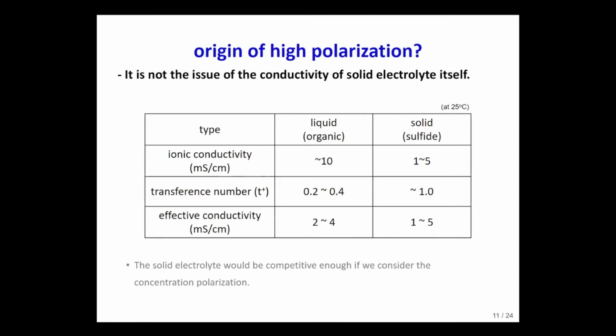Many people suspect that the lower conductivity of solid electrolyte is responsible for the low rate performance, but that is not true in this case. Typical ionic conductivity of organic electrolyte is in the range of 10 millisiemens per centimeter, but the transference number for lithium ion is only about 0.2 or 0.3. So the effective conductivity would be a single digit in terms of millisiemens per centimeter.